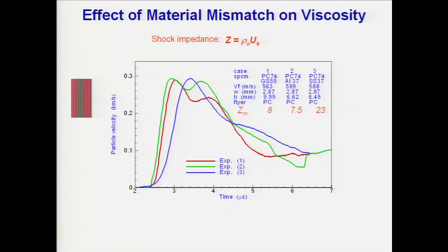So here, we look at one of the important quantities in shock physics, which is called the shock impedance, which is the product of the density times the shock wave speed, which is a material property. If the mismatch is much higher, as in the case between the polycarbonate and stainless steel, then you see a very long rise time. What that tells you is that if you have a very large impedance mismatch between the layers, then your rise time is bigger, and the effective material viscosity is higher,